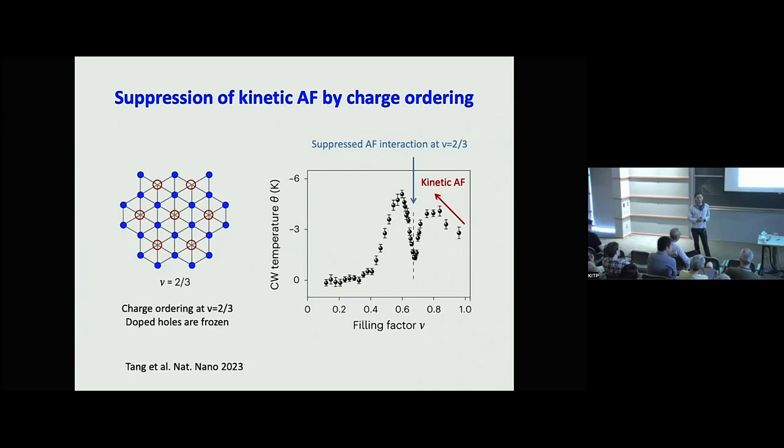Yeah. I think it's fairly typical in strongly correlated metals to see Curie-Weiss-like behavior in metals that are not so far from being a correlated insulator, but the interpretation as a strength of antiferromagnetic interactions is questionable. If you try to fit a Pauli susceptibility to a Curie-Weiss temperature, you'll get a very large Curie-Weiss temperature. That's just from the Fermi pressure of the system. So there's some combination of these effects that adds to it. This theory doesn't take into account that it's a metal.